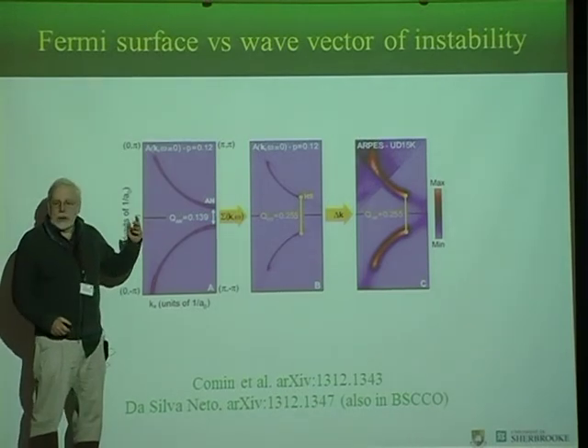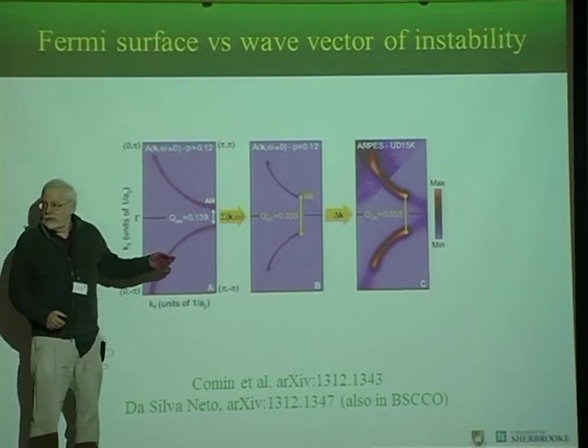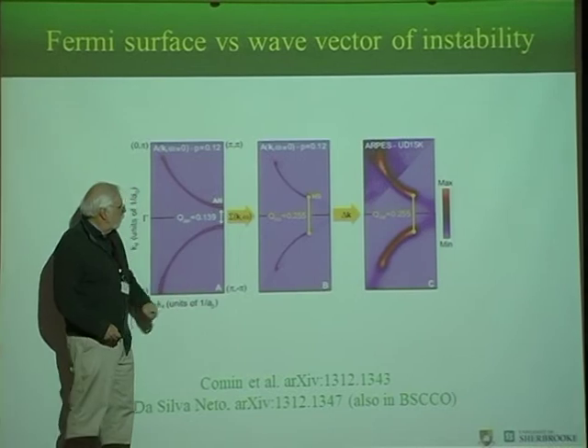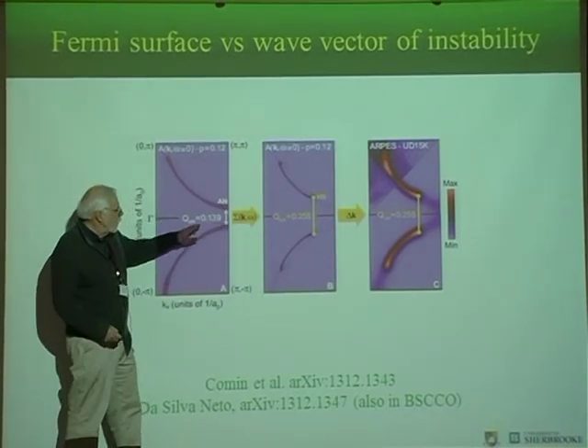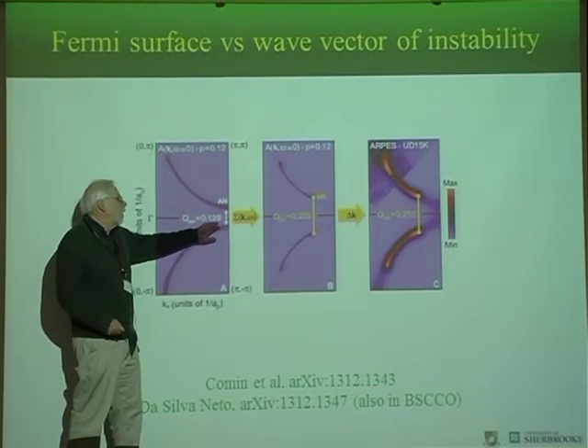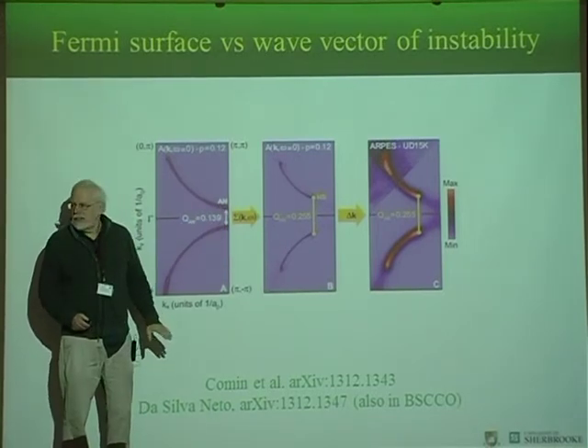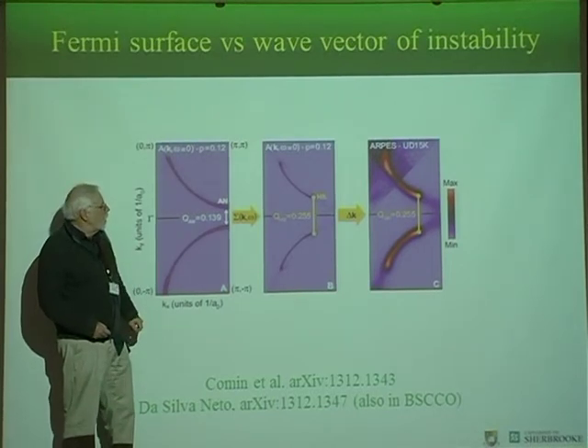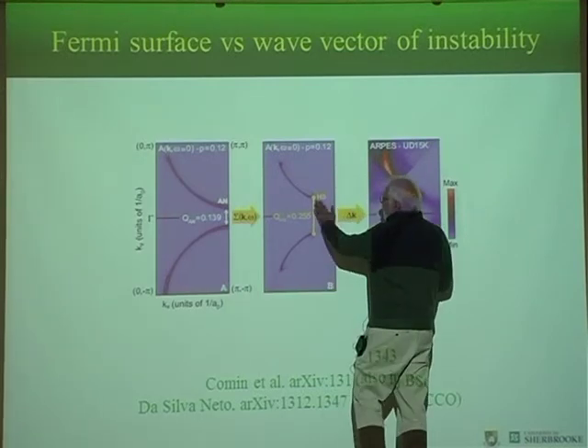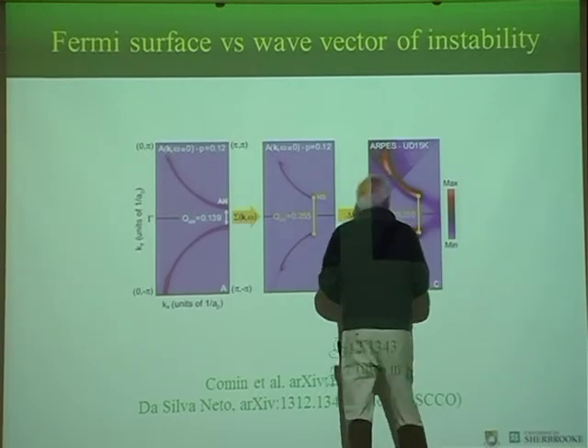Now this is the relation of this wave vector with the Fermi surface. So this is the non-interacting Fermi surface, and this wave vector is close to what is observed experimentally, but actually it's a factor of 2 or so off, almost 3. Now, if you remember, I showed you the picture for the electron-doped case. For the hole-doped case, it's this piece of the Fermi surface that disappears. So if you just get rid of this piece and look at this, you get closer to the actual value. And in fact, if you put back the broadening that comes from interaction, you get something pretty close.